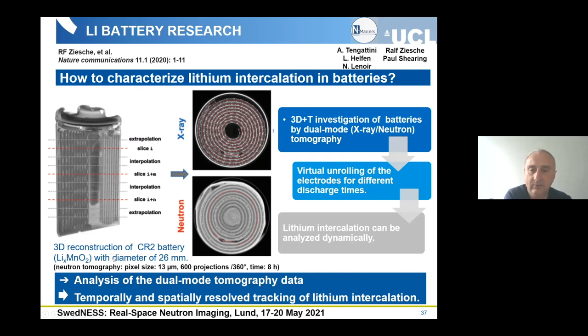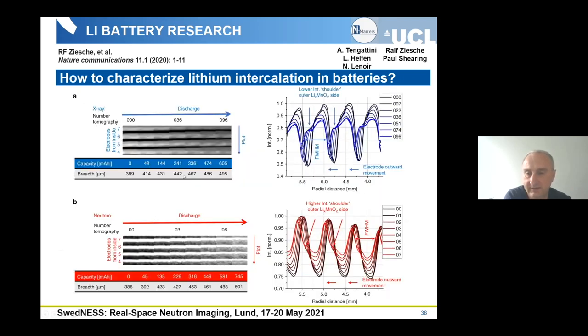And here we can combine the high resolution of the X-rays with the complementary contrast provided by the neutrons, where we can see the distribution of the lithium. Here we also used some innovation where this curved, or let's say rolled, structure can be unrolled. In this way, we can investigate just planar structures, which is much more convenient for the investigation.